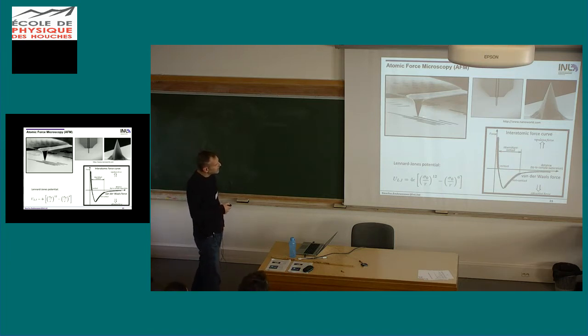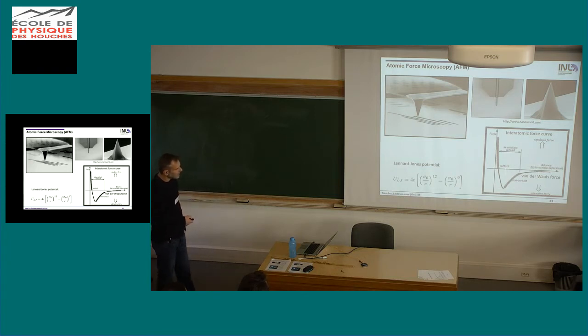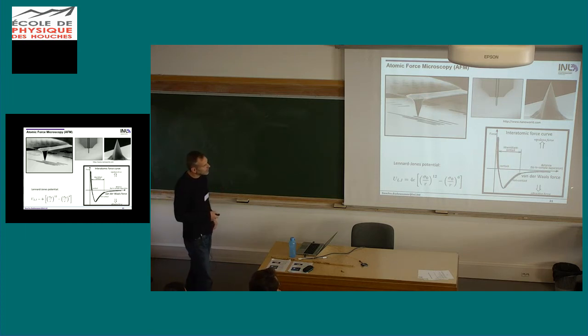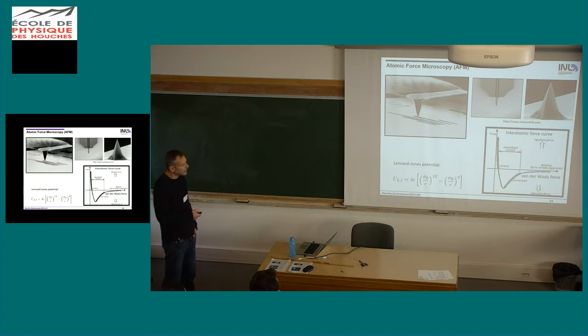And what governs the interaction between the sample and the tip is this force distance curve. So if you go very close, let's start here. If you're far away with your tip from the sample, there's of course no interaction. Now you get closer and closer, then at some point the van der Waals forces become important. These are attractive forces between tip and sample atoms.